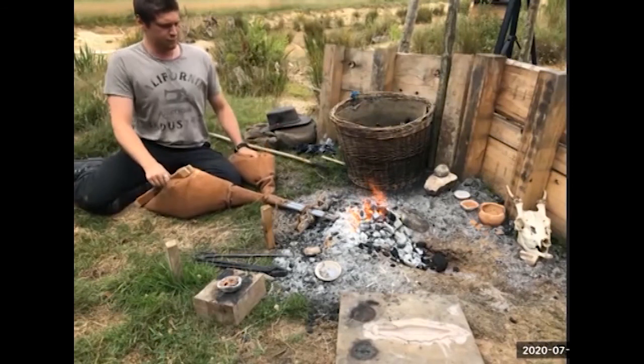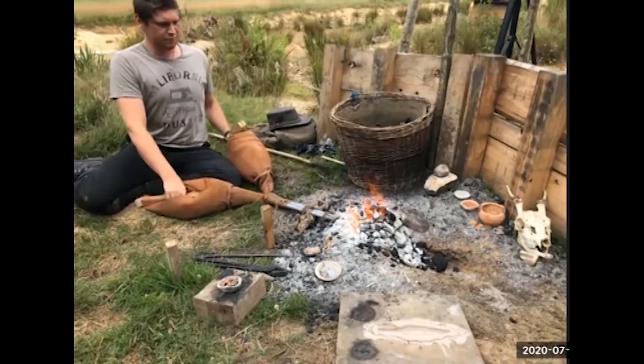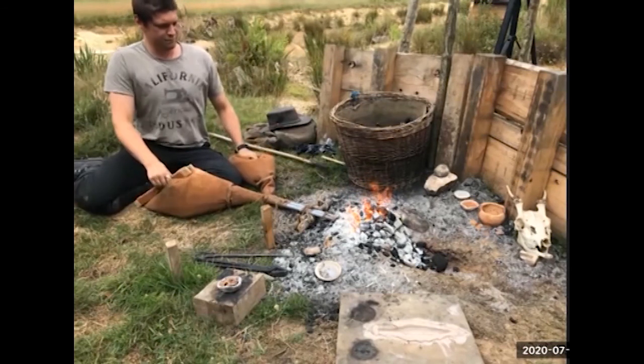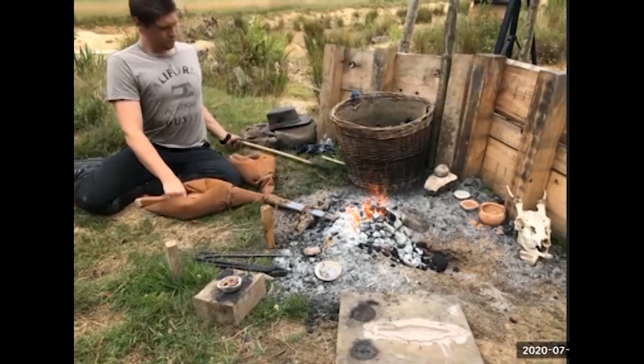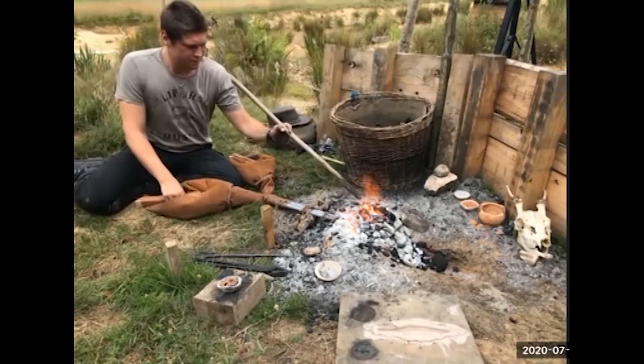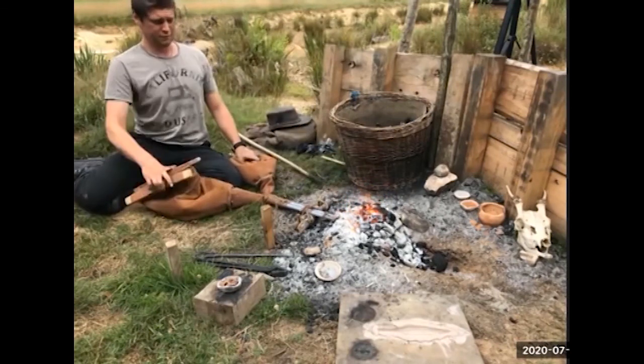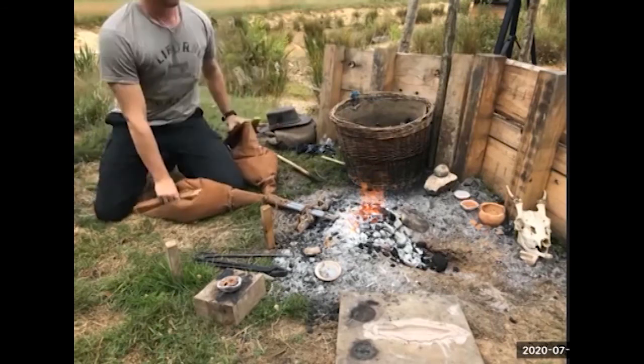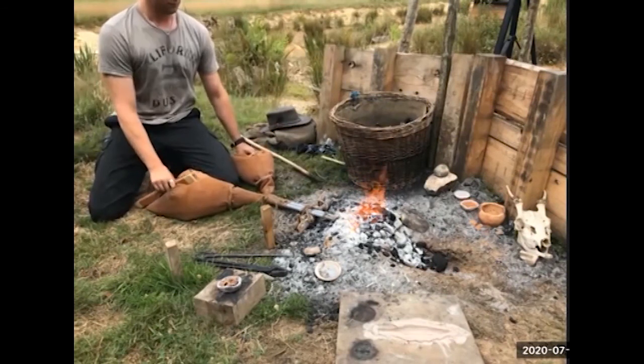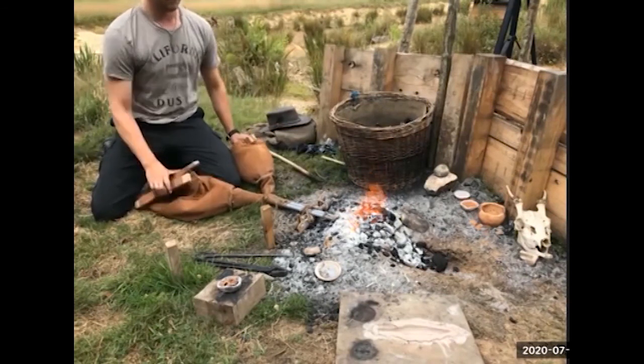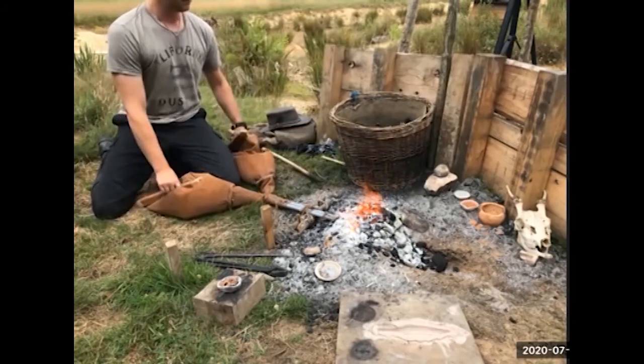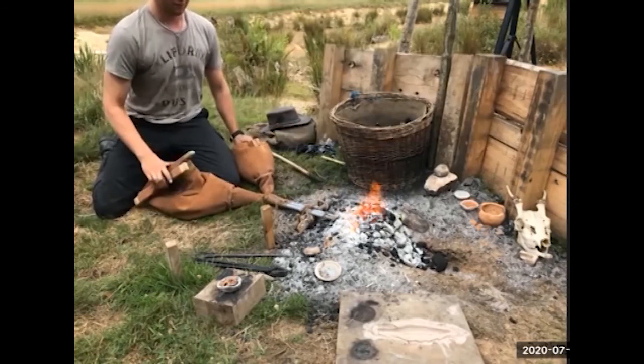So the surface of the crucible will be melting with the flux of the ash, the alkali of the ash from the charcoal will be facilitating a glass even forming on that crucible, and that will be reacting with the metal that's melting, and it's a very, very unpredictable process. And even in modern foundries, there's a 1 in 3 failure rate with castings, which is incredibly high.